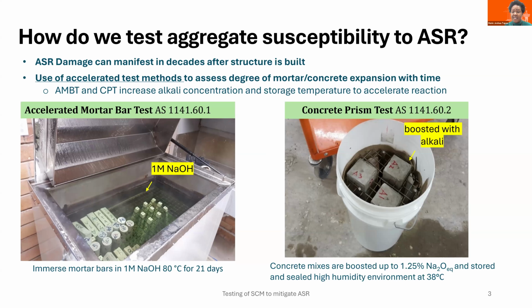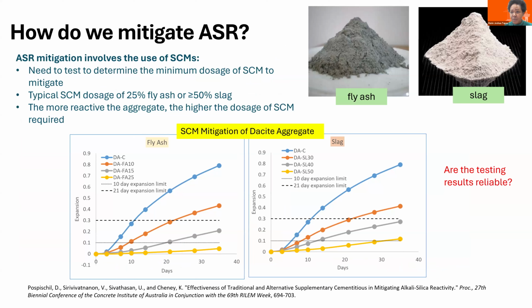Therefore, we use accelerated test methods to assess the susceptibility of aggregate to alkali silica reaction. As you can see from the screen, we have two in Australia, the accelerated mortar bar test and the concrete prism test. Both test methods rely on increasing alkali concentration as well as storage temperature to accelerate the reaction. Then we plot the expansion of the system with respect to time to assess whether we have a reactive aggregate or not. Ideally, we don't use a reactive aggregate, but in cases where we don't have the luxury and we still have to use them in the concrete mix, what do we do to mitigate?